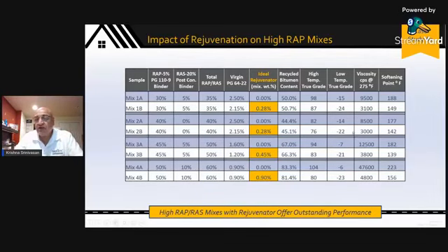You can see that the low temperature performance, by the way, this is important because it tells you how resistant your material is to cracking, how resistant your material in some ways also tells you about fatigue damage tolerance. The lower the number, the better. You can see how much of a dramatic impact rejuvenation makes to the low temperature properties of your material. Right away, you can see that the viscosity is reduced to about a third. And that makes it much easier for pavement laydown. You're not dealing with a stiff mix that you have to overheat in order to put down on your pavement.